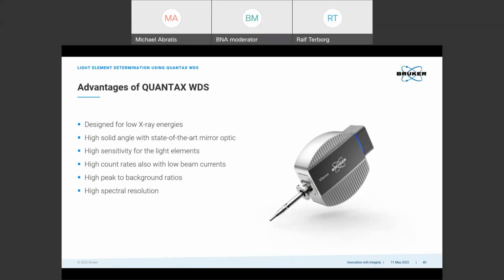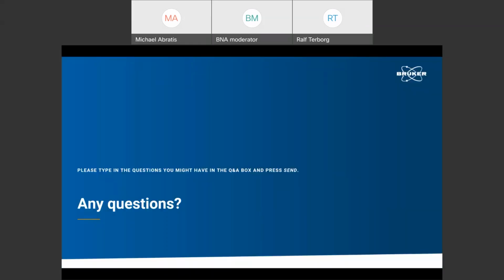Let me give you some details on the analytical conditions. Low kV is optimal for light element analysis. In the diagram on the upper left, we see an example for boron K alpha with an optimum peak intensity at 4 kV acceleration voltage. The optimum depends on the number of ionizations, which increase with an increasing excitation volume, and it depends on the absorption factor on the other hand. A larger excitation volume means an increased path length and thus a higher probability for absorption of a photon. Remember that absorption is an important factor for the light elements, as Ralf pointed out earlier.